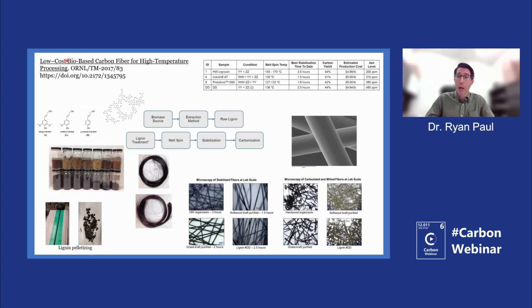In this work that we did, we showed that you can take different biomass sources. In this case, we looked at some softwoods, some hardwoods, and some true kind of waste biomass, and by using different extraction and cleaning methods, we could get to a raw lignin that could be melt spun into fiber. And we looked at some different treatments. We looked at some plasticizers. We looked at some stabilization accelerants to help shorten the stabilization time. But we could get to some acceptable carbon fibers that could be milled and still retain their shape and integrity, for example, for use in an insulation application.